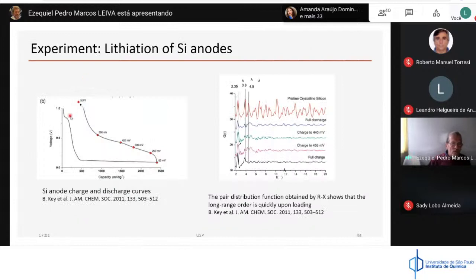This is a typical curve for charging. This is the voltage as a function of capacity. This is a galvanostatic charging. You get this curve, and this is hysteresis. You have a strong change in the curve. This is not good for the battery. And the same thing happens here.